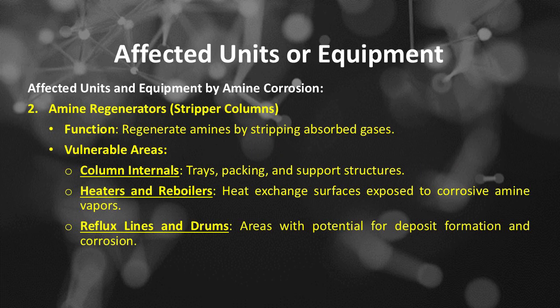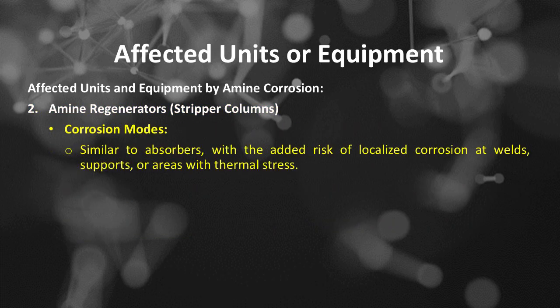Affected units and equipment by amine corrosion. Number 2 is amine regenerators, stripper columns. The function of stripper columns is to regenerate amines by stripping absorbed gases. Vulnerable areas of stripper columns include column internals, trays, packing, and support structures, heaters and reboilers, heat exchange surfaces exposed to corrosive amine vapors, reflux lines and drums, areas with potential for deposit formation and corrosion. Corrosion modes commonly occurring on amine regenerators, stripper columns, include, similar to absorbers, the added risk of localized corrosion at welds, supports, or areas with thermal stress.